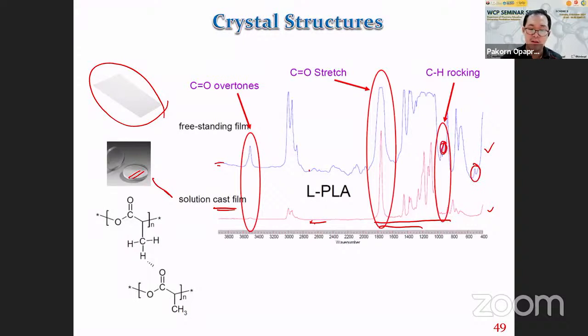This region can give important information. If you look at this region, the peak is very small. If you want to have information from this region, what should you do? You can increase the thickness of your sample to get this peak bigger. But when you do that, you sacrifice something. Some big peak here will be overabsorbed, that is not suitable for use anymore. However, you get information from the small peak. So you can use these 2 spectra to get the full set of information that you want.